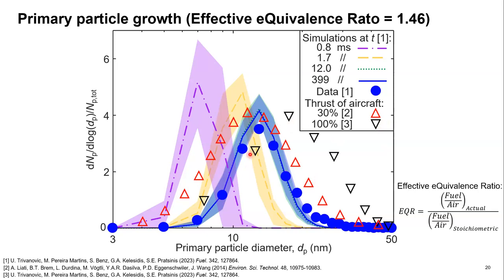And indeed, we see that our data do fall in between these two extremes, and the tails of the distribution line up quite well. So the left-hand tail of our distribution lines up well with the 100% thrust soot, and the right-hand tail of the 30% thrust lines up well again with ours. So further confirming that the size distributions are similar to that from real aircrafts.